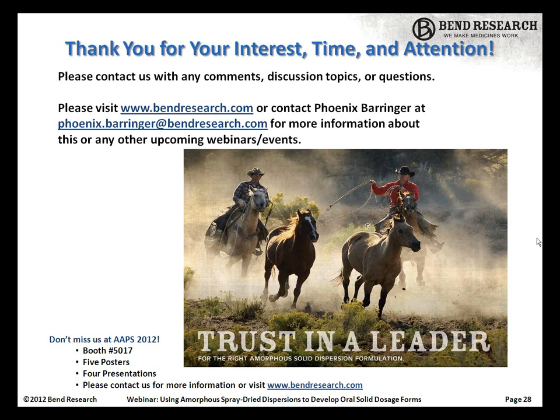I'll answer that from two levels. The first one from a performance standpoint, where I'm defining performance as the dissolution performance. From that standpoint, we view there as very little difference. Generally speaking, they're equivalent. There are some cases where dry granulation will afford us some other flexibility that direct compression won't. That isn't so true for the enteric polymers. For the non-enteric polymers, we will manipulate the ratio of intragranular and extragranular, so for those, more often than not, we will lean towards using dry granulation. But for the enteric polymers, in particular HPMCAS, we would consider them interchangeable. So that's the performance side of it.